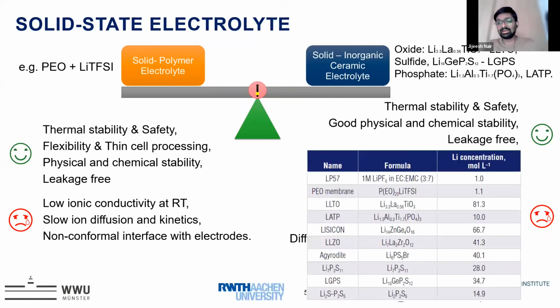Besides, again in reference to Professor Ruffo's talk, we need to use a lot of lithium. For example, in a simple liquid electrolyte system, one mole of lithium is used per liter. However, if you move to the solid state system, for example LLTO, 81 moles of lithium is used. This increases the amount of lithium that is used per battery or per cell. So this is also a good challenge.